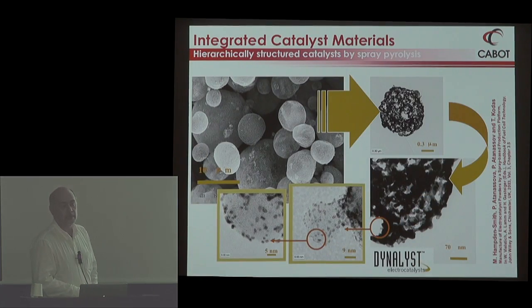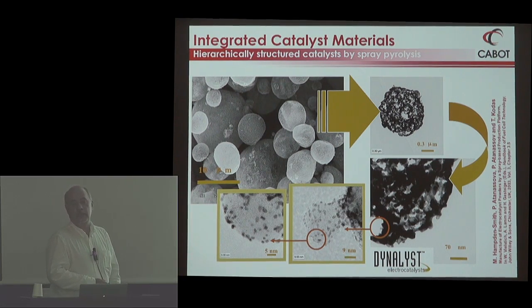And the catalyst that is made by that method is manufactured by Cabot Corporation, which purchased Superior Micropowders, and the catalyst trade name is Dynalyst. That catalyst is one-to-one platinum-ruthenium nanoparticles deposited on carbonaceous material, and that carbonaceous material, it's actually carbon black, is packed into spheroidal aggregates that are controlled essentially by the flow and the atomization of the precursor.